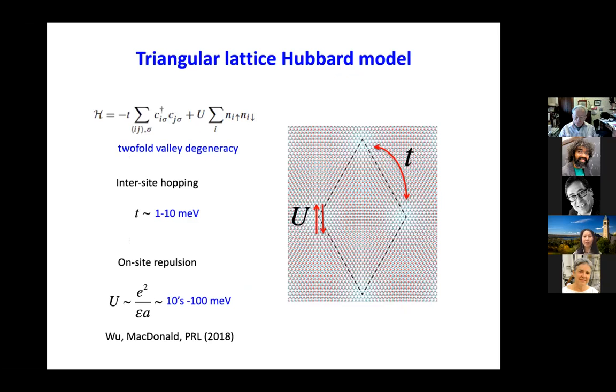And it turns out that this system is very well described by a single band Hubbard model, as shown by Fengcheng Wu and Allan MacDonald almost 3 years ago. So in this case, the spin degree of freedom is replaced by the valley degree of freedom. So I showed you there's a K point and a K prime point, and you can think of those as a pseudo spin. So the parameters have been estimated. The hopping parameter here is between 1 and 10 meV, and on-site repulsion is on the order of 100 meV. So now we have energy scales somewhere intermediate between real solids and atoms in optical lattice systems.